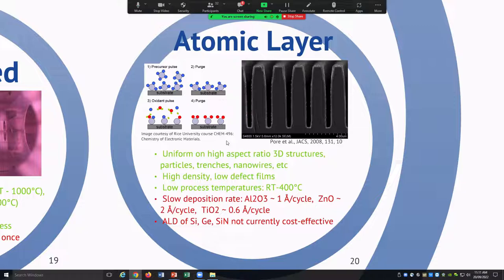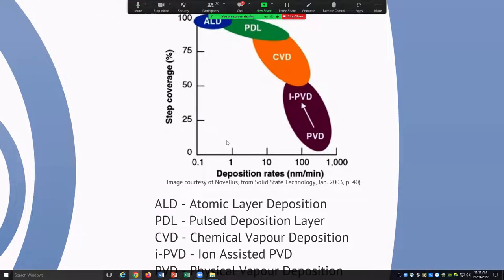So we've got sputter, we've got thermal, we've got PECVD, and we've got ALD. How do they stack up? We can see a nice graph here. You're talking step coverage and then deposition rate. Like I said, not all coating techniques do everything. If you want 100% coverage, then your only choice is atomic layer deposition. If you want to go fast and don't really care about how uniform your coating is over complex structures, then sputtering or thermal evaporation fits in here. And then you've got these two CVDs kind of in between. And those are the typical deposition rates we're talking about, so you're in the 0.1 to 1 micron a minute sort of region.